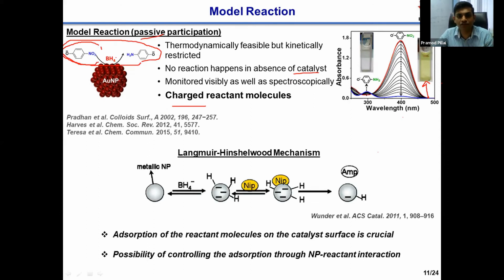And the mechanism, as I have told, is well understood. It follows a Langmuir-Hinshelwood mechanism. Again, I'm not going into the detail, but what this mechanism tells us is that both the reagents, borohydride and the nitrophenol, get adsorbed on the surface of the nanoparticle, and then there is a hydride ion transfer. So this indicates that the attraction of these reactants to the nanoparticle surface is crucial. And for this reason, this becomes an ideal model reaction for our studies.